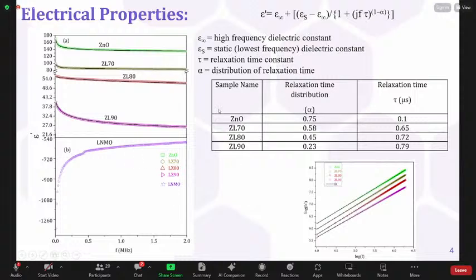And to understand the relaxation model, the UDR model, universal dielectric response, was also recorded, and it shows that as we increase the content of LNMO, the slope decreases, which shows the dielectric constant is decreasing.